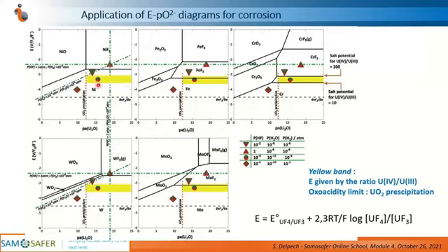And we see that when the ratio is equal to 10, nickel is not oxidized, iron is not oxidized, chromium is at the limit of its oxidation, and it's okay for tungsten and molybdenum. But when the ratio increases to 100, we observe that we have oxidation of iron, chromium, and molybdenum. So we can control the redox potential using this ratio, considering these two soluble species.